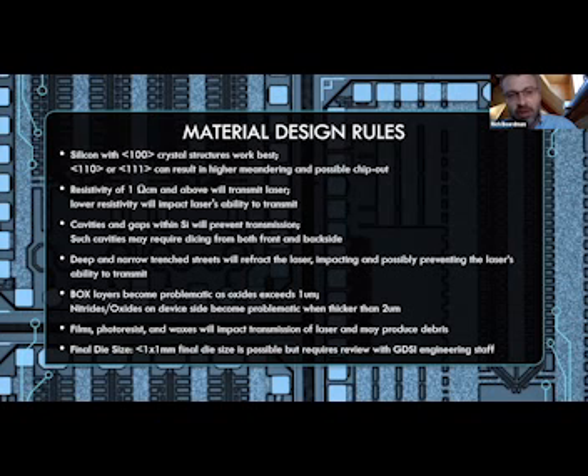If we have resistivity on the wafer of lower than 1 ohm centimeter, it typically doesn't allow us to focus the laser light beneath the surface, create those stealth layers that you saw in the sidewall of the wafer a couple of slides ago, and then allow you to separate the wafer post stealth dicing processing. So if you do have a wafer that's lower than 1 ohm centimeter in terms of resistivity, what will happen is when you go to the tape expansion step, the die will not separate, or you might have some that separate and some that don't, but it won't be the beautiful, clean separation and 100% singulation that we would expect.